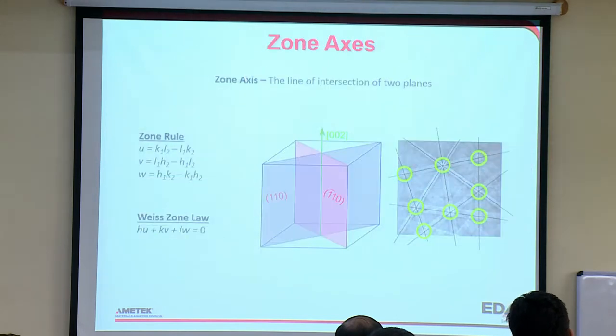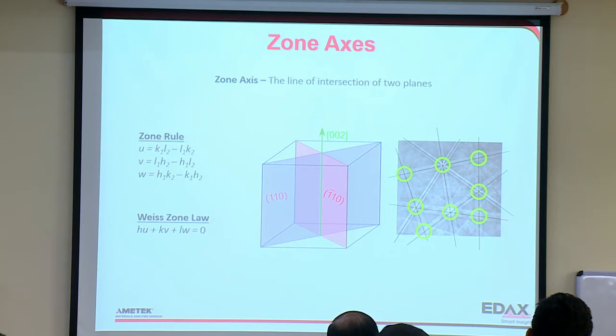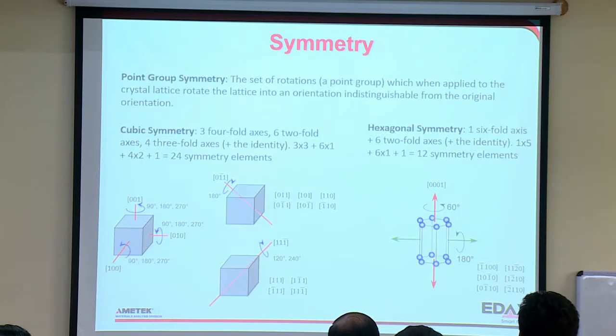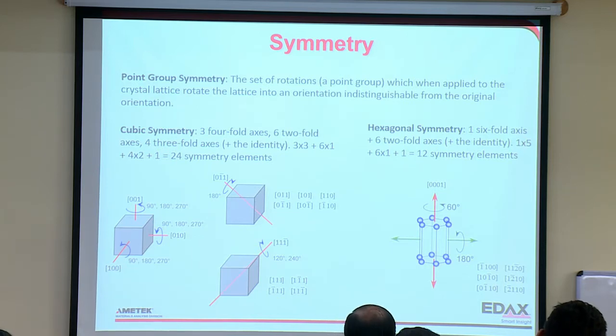Now, when planes come together, we call those zone axes where they intersect, and they correspond to poles in our material. And this all comes into play because of symmetry, and we generally worry about point group symmetry in EBSD, although really we worry about Laue group symmetry, and I'll come back to this idea. So point group symmetry defines the set of rotations, which is a point group, which when applied to the crystal lattice rotated into an orientation that can't be differentiated from the original orientation. So for example, if I take an 001 axis here, rotate it 90 degrees about that, this cube will be in an orientation I can't tell the difference.